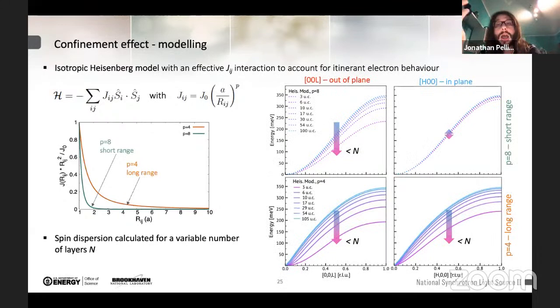Based on this model, the spin excitation dispersion was calculated for in-plane and out-of-plane directions. What we observed was that for the long-range interaction, we had a softening of the spin excitations as a function of thickness that is to the same extent between the in-plane and out-of-plane directions. Whereas when we used a short-range J interaction, we observed a softening along the out-of-plane direction, but in the in-plane direction, we observed a much smaller softening of the spin excitation.